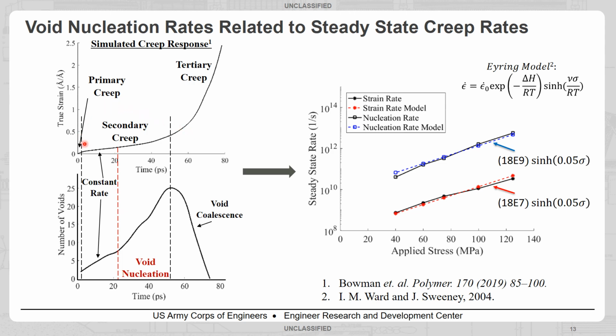We were also able to show that in the secondary creep regime, the dominant damage mechanism is void nucleation. We see this rapid increase in the number of voids, but once tertiary creep happens and deformation starts to speed up, leading to fracture, that is induced by rapid void coalescence, where the number of voids rapidly decreases due to these void surfaces merging. So we were able to provide both qualitative and quantitative information here using these MD simulations. We also could show that void nucleation was directly related to structural changes such as disentanglements. So if you're interested in this, please see this 2019 paper that we published in Polymer.